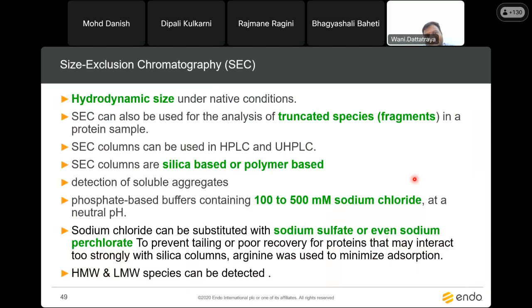Size exclusion chromatography, as I explained, is based on a chromatographic principle. The separation is based on the hydrodynamic radius, nothing but the molecular size of the molecule. The molecule having the lower molecular weight gets retained in the pores. Molecules having the high molecular weight will not be retained and will elute earlier. So if any aggregates are formed in your molecule, that peak will elute earlier. If any peak is eluting earlier, it represents that there is a formation of aggregates or agglomerates in the molecule.